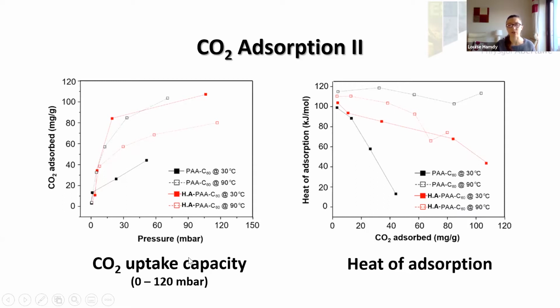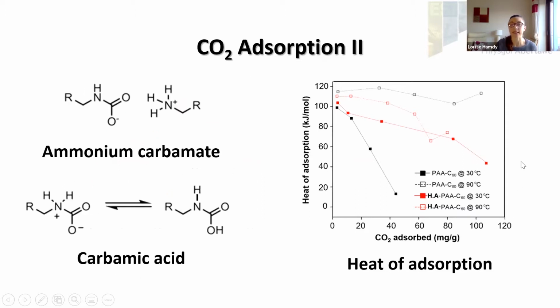Now, we use microcalorimetry to measure the heat of adsorption. This is the heat released on adsorption of CO2 at each of these points. And we plot the heat of adsorption against the quantity of CO2 adsorbed. Now, we see first that the heat of adsorption is highest for all the materials on first contact with CO2. So very high, about 100 to 115 kilojoules per mole on first contact. And this is due to the abundant amines on both materials and the formation of the chemisorption interactions, whereby we form ammonium carbamate and carbamic acid species.